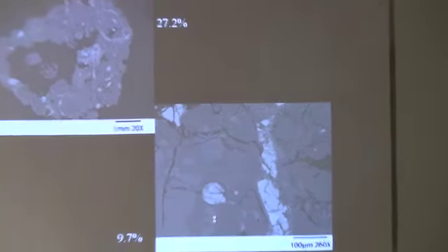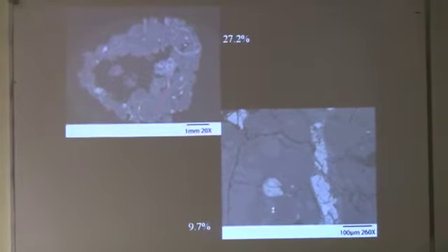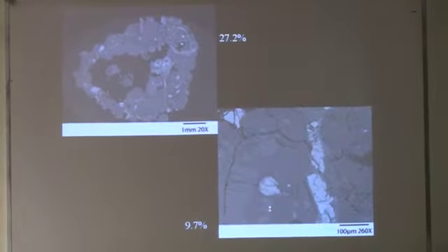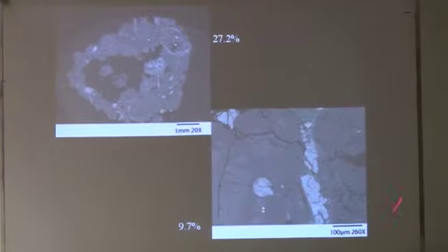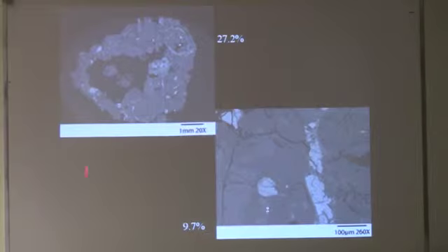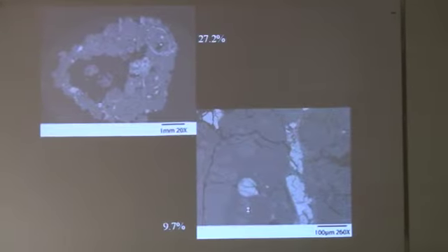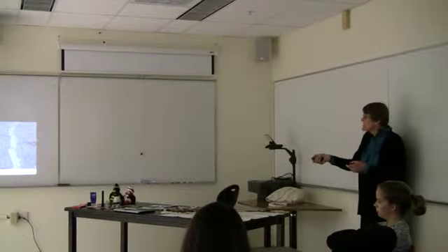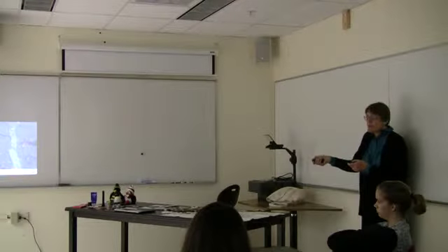That's a real hole. And so that thin section on that sample has up to 27%. So I'm suspicious that some of the porosity that we're seeing in those carbonaceous chondrites may be the very nanoscale porosity. It's definitely not the microscale porosity we tend to see in the ordinary chondrites, but I think a lot of it is these big macro scale voids that when I measure on a thin section, I look at this and say, well, it's a big pit at the edge of the thin section or something like that, and I don't count it.